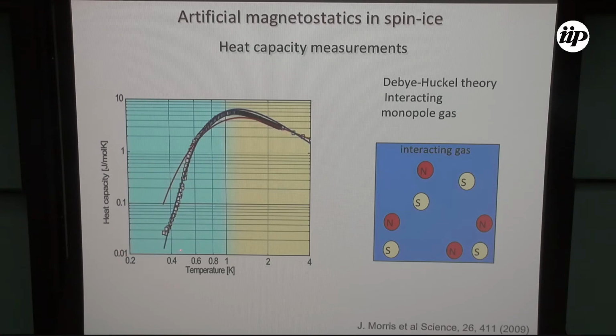So this is the measurement we did. This is heat capacity as a function of temperature. What's relevant is below 1 K. So as I said, you need to be at low temperatures, because otherwise, if you have many of these excitations, it's no longer true that you're looking at a long length scale picture.